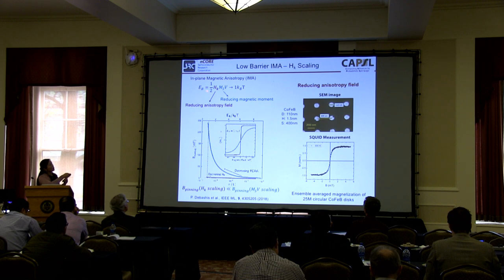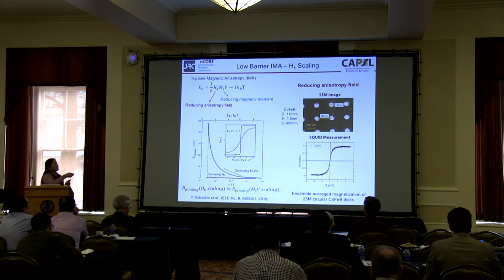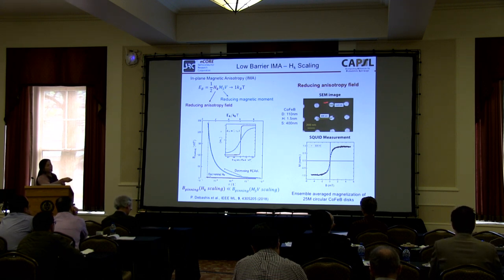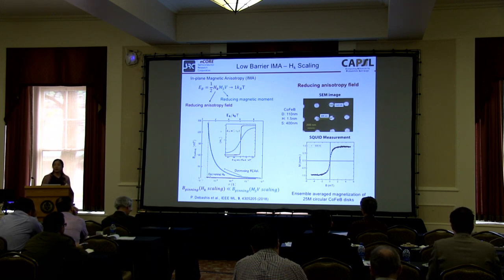So for the magnets, we know the energy barrier is a product of the anisotropy field and the magnetic moment, Ms times the volume V. So you can either scale down the anisotropy field, HK, or you can work on the MsV, trying to make the volume or the Ms small to make your energy barrier small. So here, in the first case we try to reduce HK. How do we reduce HK? Basically by patterning the magnet into a perfect circle. Once I have no easy axis, no in-plane anisotropy field, then each magnet, each disk that I show in the SEM here, is going to have its magnetization rotating 360 degrees in plane.